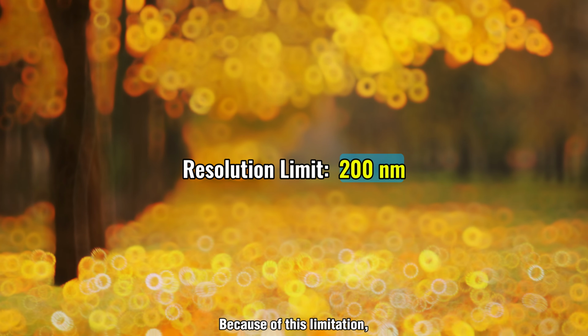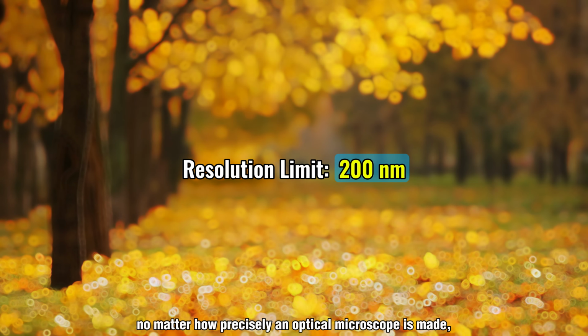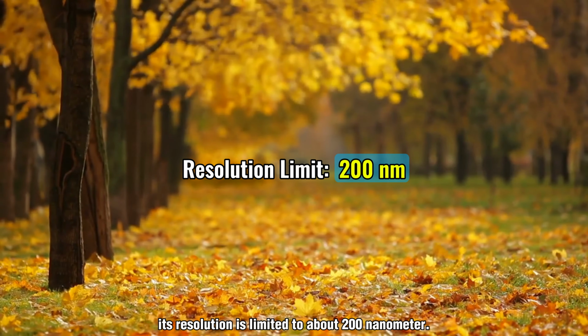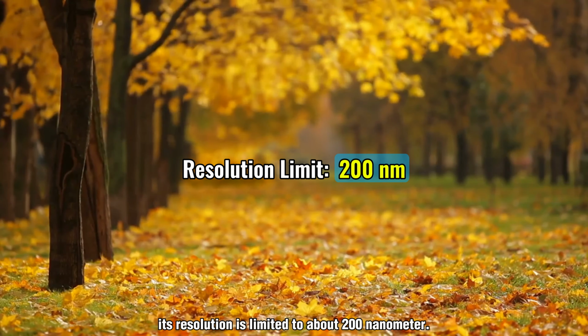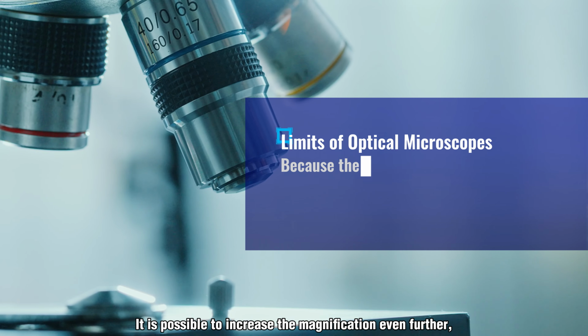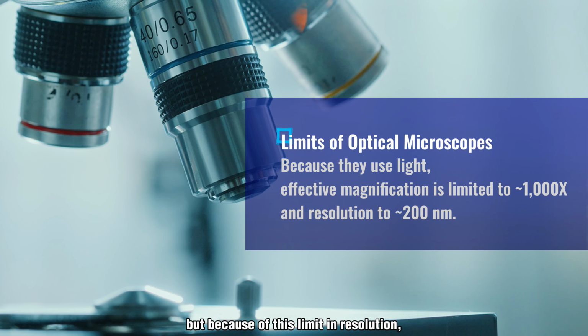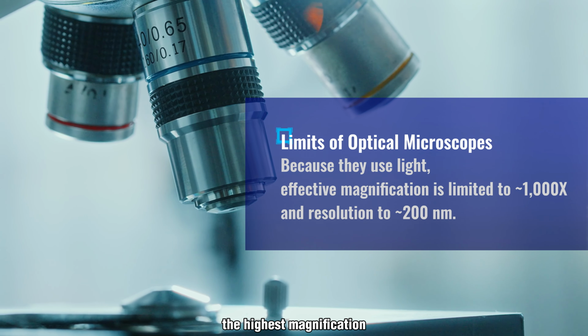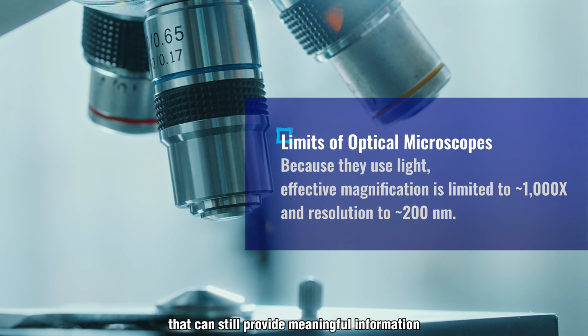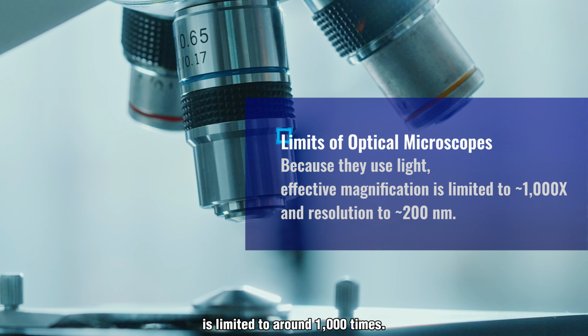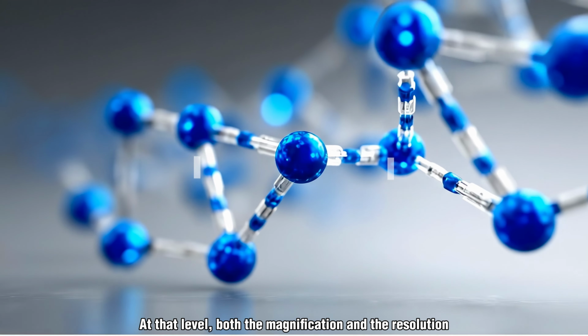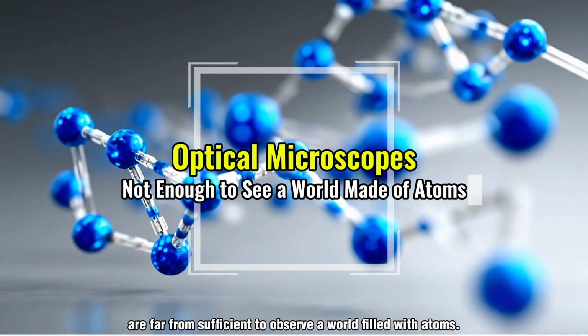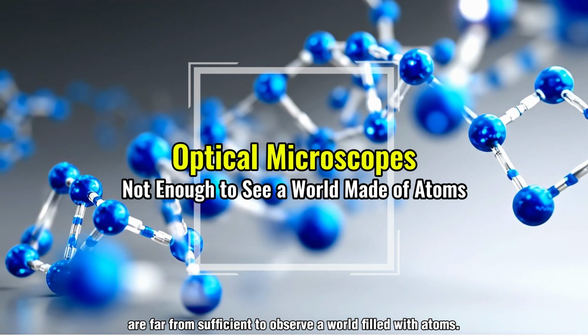Because of this limitation, no matter how precisely an optical microscope is made, its resolution is limited to about 200 nanometer. It is possible to increase the magnification even further, but because of this limit in resolution, the highest magnification that can still provide meaningful information is limited to around 1,000 times. At that level, both the magnification and the resolution are far from sufficient to observe a world filled with atoms.